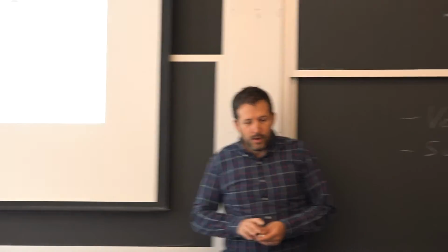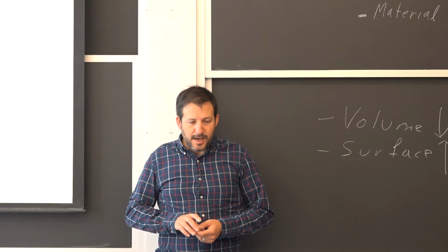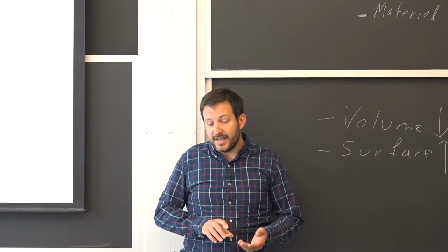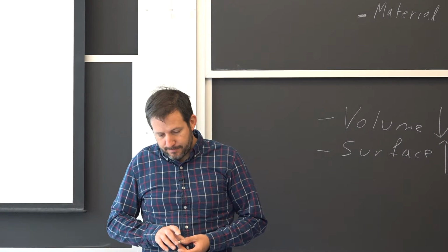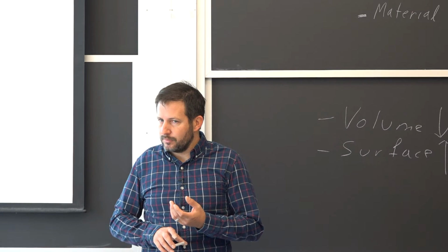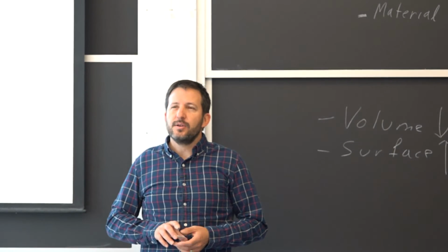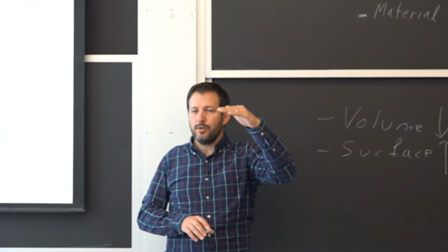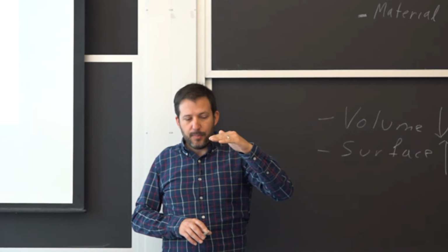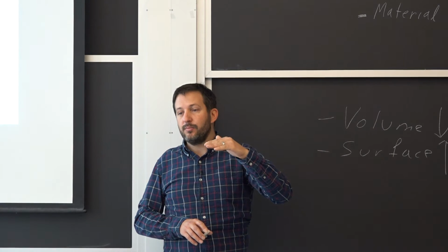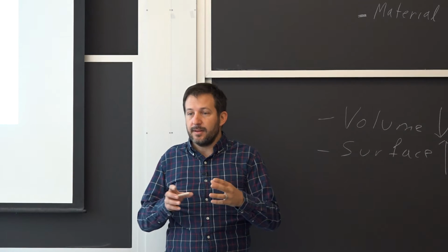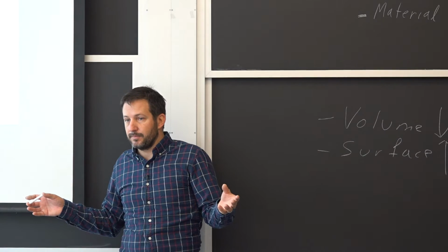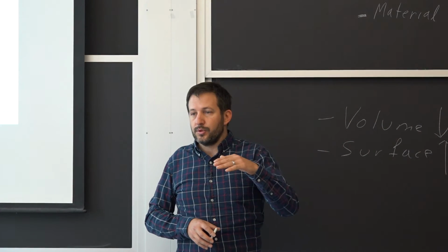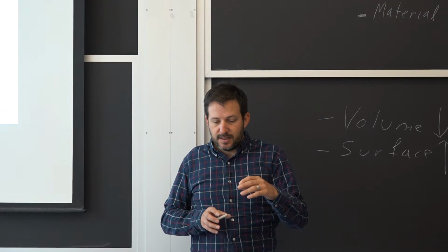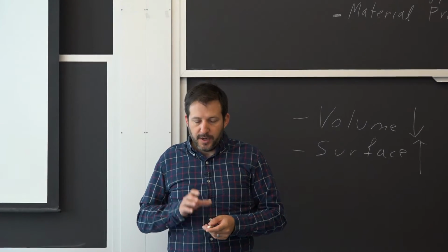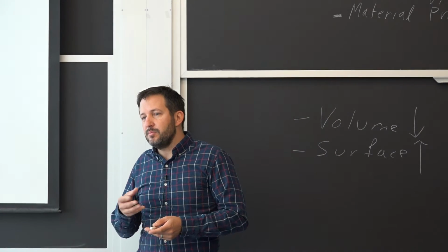So let's say I want to make an aluminum casting that has a very, very fine microstructure. What I'm trying to do, I could do two things. I could keep the temperature just below the fusion point, and then it's going to take a while before something starts to form, and then that thing that forms is going to grow very, very quickly. That's very typical. If I lower the temperature, I get these little nuclei that are going to form very quickly, but then they take more time to grow, and that gives me a better microstructure.